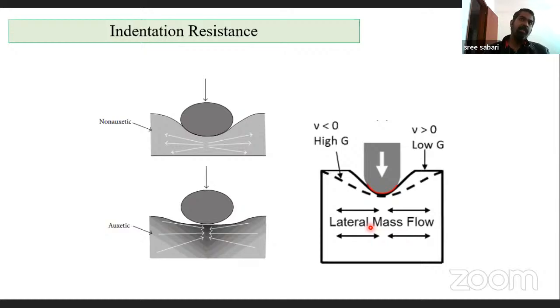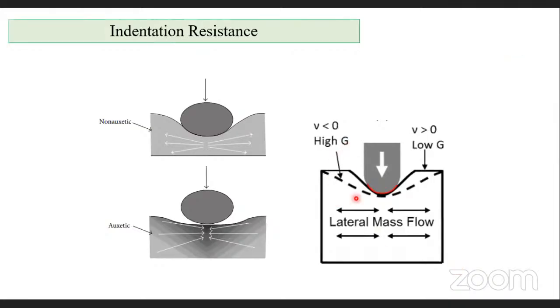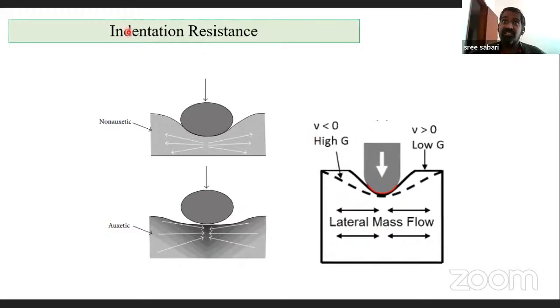Again, I'm saying that you need to tailor these mechanisms in order to make it beneficial. If I'm saying auxetic material, it is not completely beneficial. You need to tailor that. You need to alter or optimize the behavior in order to fit your applications. As I told before, if you have a higher shear resistance, this will also have an influence on creating indentation resistance. So the Poisson ratio is associated with shear resistance, and the shear resistance is associated with the indentation resistance.